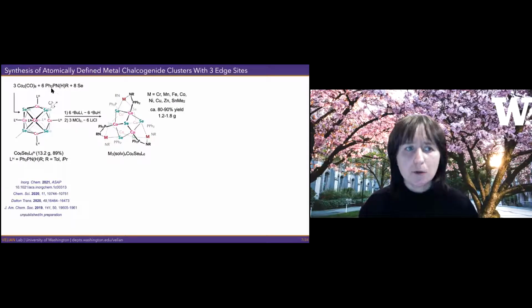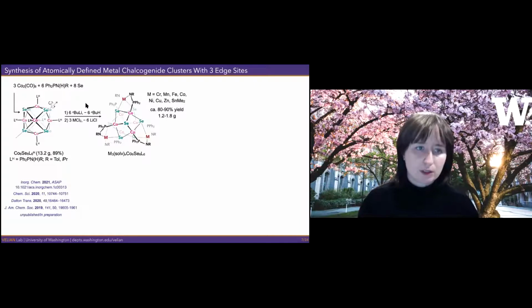So we use an aminophosphine to do that. We cap the cluster with it, and it turns out that that amine, upon deprotonation, enables these 3 coordination sites on the surface of the cluster. So I have 1, 2, and 3, and we can install, using deprotonation and then treatment with a metal salt, a really wide range of metals.